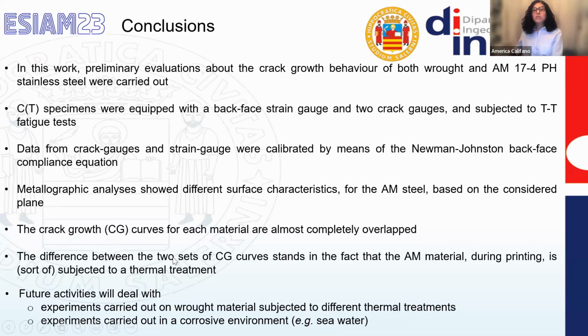The difference between the two sets of curves stands in the fact that the materials do not have the same microstructure, and the wrought material was not post-treated, while the additively manufactured material during the printing phase is sort of subjected to a thermal treatment, so a sort of hardening. Finally, future activities will deal with carrying out experiments on the wrought materials subjected to different thermal treatments in order to better compare the results with the additively manufactured stainless steel. Further experiments, which are in progress, as my colleague showed in his previous presentation, will be in a corrosive environment, especially in seawater, in order to investigate the stress corrosion cracking phenomenon.